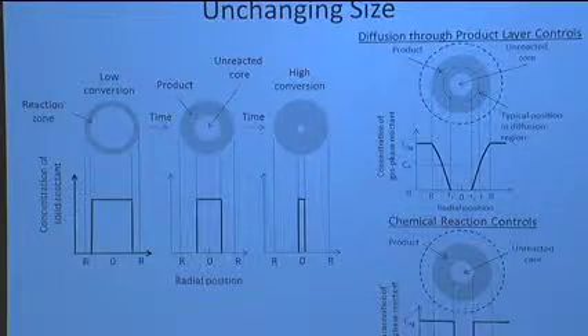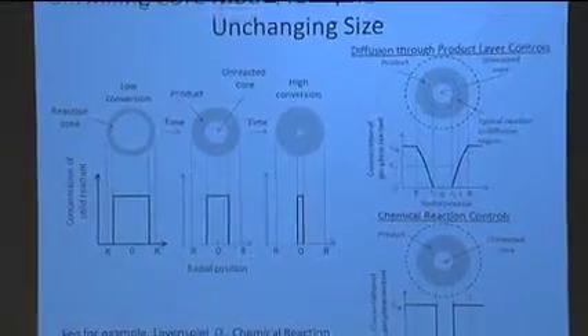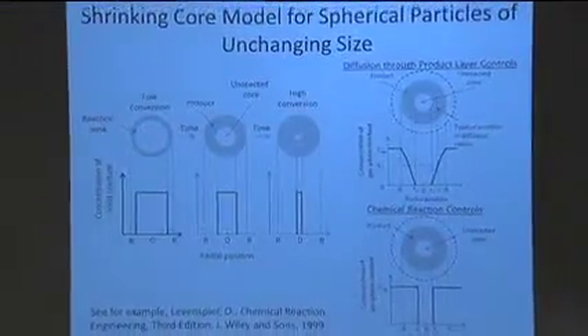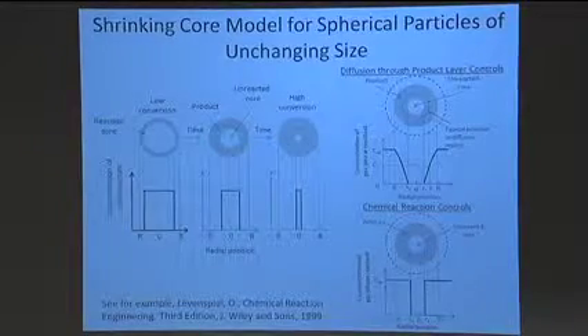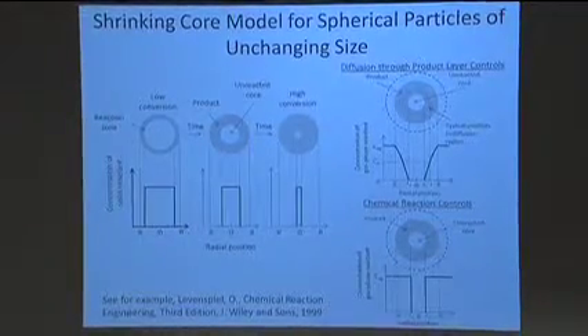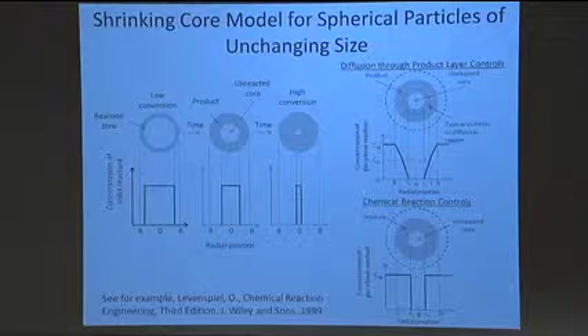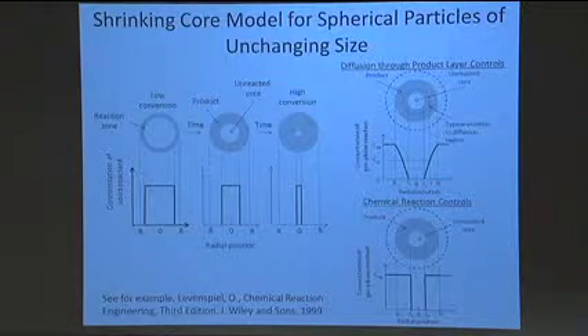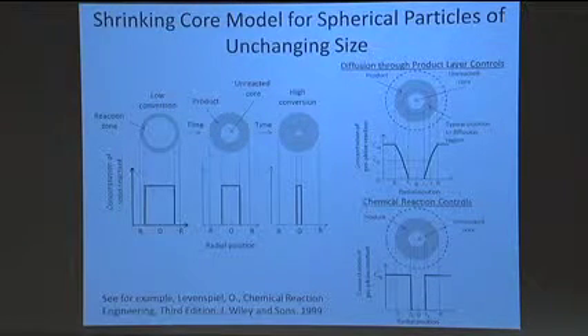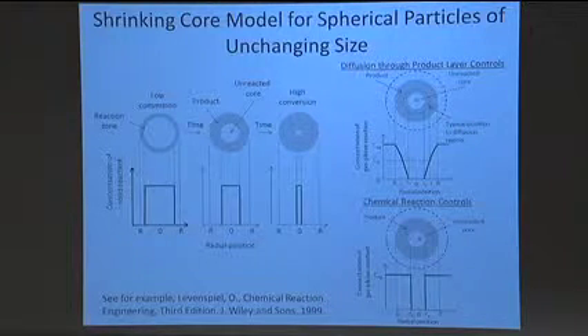And if that's the case, one can look in, say, the chemical engineering literature at what's been done in terms of how coal might react in a shrinking core model with an unchanging particle size. So this would be the case that I was just illustrating. Suppose now I'm burning aluminum nanoparticles, and the environmental temperature is below the vaporization temperature. I know the product is a condensed phase compound, and so it's typically going to be formed on the surface.